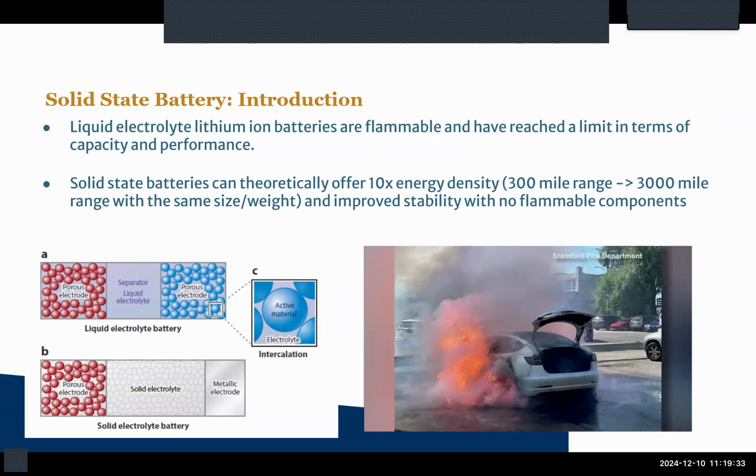It goes from the cathode during the charging state to an anode material, where it then either intercalates into the anode material or plates on top of it. So the plating would occur as the preferred method of charging in, say, lithium metal, where that's really the only option. And so, yeah, during charge, lithium goes from cathode to anode and then back again. This happens because you're putting the system out of equilibrium by imposing a potential difference, which then induces a current.